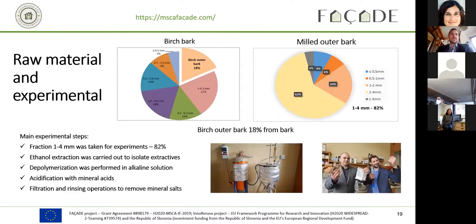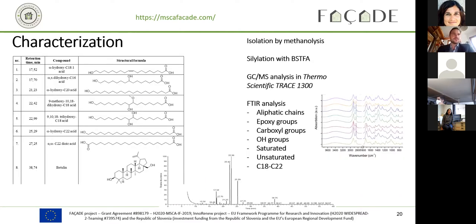As I mentioned before, birch bark was used as a raw material. We made ethanol extraction to isolate extractives. Then the depolymerization was carried out in an alkaline solution. After that, acidification was performed with mineral acids, and filtration and rinsing operations to remove mineral salts from the binder. Then we also did characterization of the raw material by chromatography and identified C18 and C22 suberinic acids with carboxyl and hydroxyl groups, saturated and unsaturated.